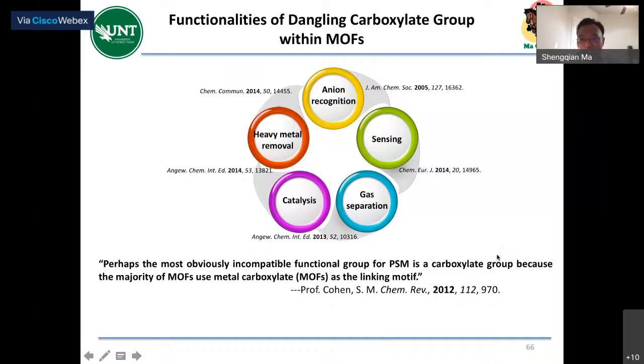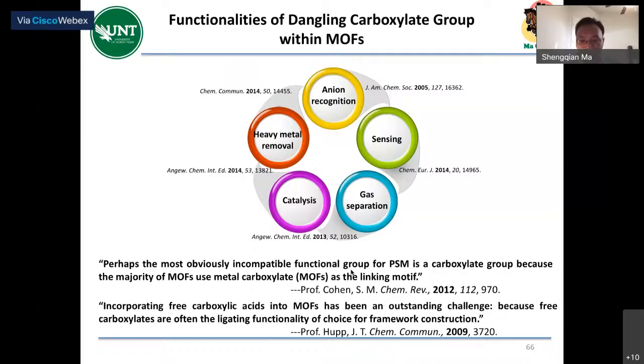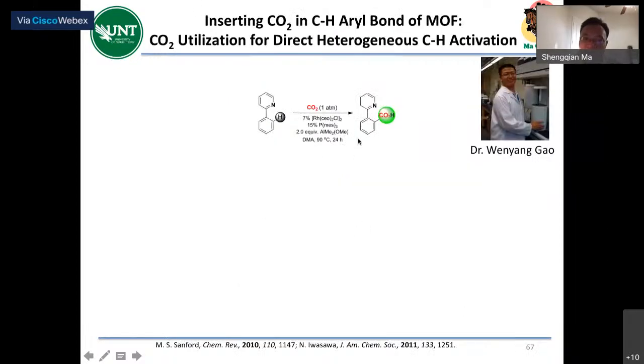incompatible functional group for the post-synthetic modification, called carboxylate, right? It forms the bond as a linker. Also, Professor Hupp also highlighted carboxylate-free as a very outstanding challenge. So what we are thinking: can we insert the CO2 in the MOF phenyl to become a free carboxylate to do something directly in the MOF? Of course, to prove this, we need first to make it feasible in a homogeneous system before we can do it.